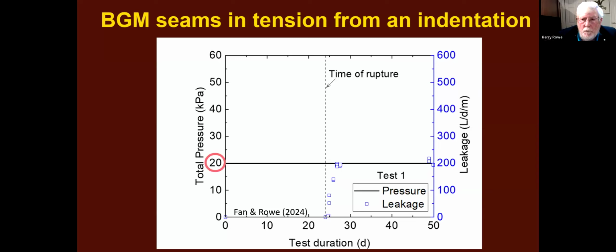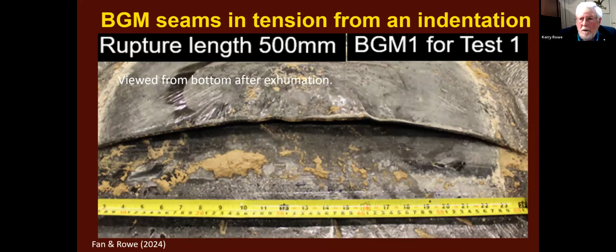But just to recap, 20 kilopascals of applied pressure, that's where it ruptured. 200 litres per day per metre under 1.2 meters of head, not a large head. And this is turning the seam upside down, so you're viewing it from the underside, and the rupture length was about 500 millimeters. So it obviously began at one location and then propagated, is what you infer from looking at the rate of increase in the leakage.